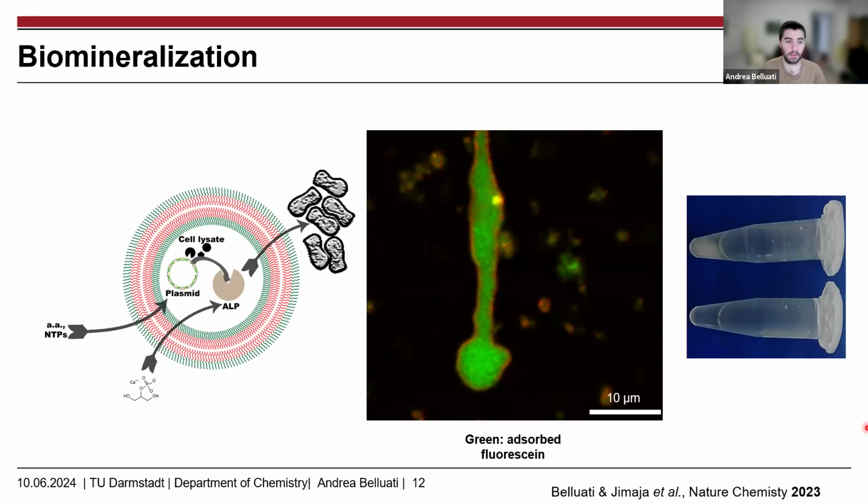And beyond that, I also tested other proteins, for example, alkaline phosphatase. Now, alkaline phosphatase is a classical protein that is used in colorimetric assays, but it can transform this substrate, which is calcium glycerophosphate, into calcium phosphate. This is a non-soluble mineral that then precipitates, thus making this kind of triggered biomineralization.